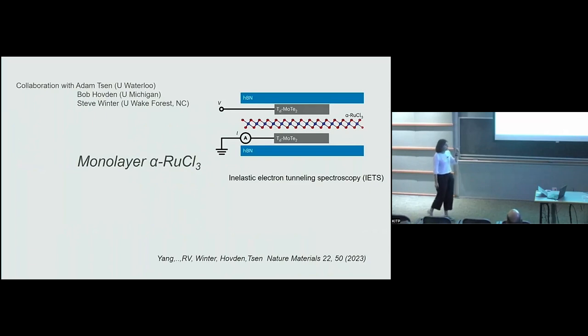But what I would like to show now are very recent experiments. This is done in the group of Adam Tsen at the University of Waterloo, Bob Hovden, and Steve Winter, who was a previous postdoc in Frankfurt and now is at Wake Forest University. What Adam Tsen did is he really managed to get alpha ruthenium trichloride monolayers. He takes this monolayer and encapsulates it between two metals.